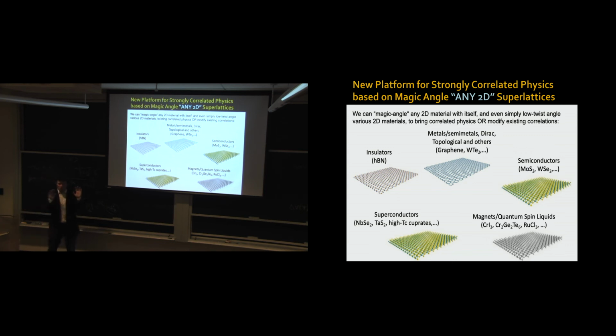And all of these materials, you can take one and put it on top of itself, and in some cases, different materials on top of each other. By choosing either a magic angle, or in many cases just a small twist angle, if the material didn't have strong correlations like graphene, you will introduce strong correlations. If the material was already correlated, you will modify those correlations.